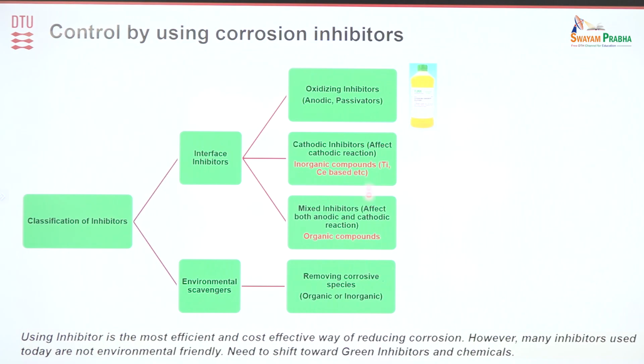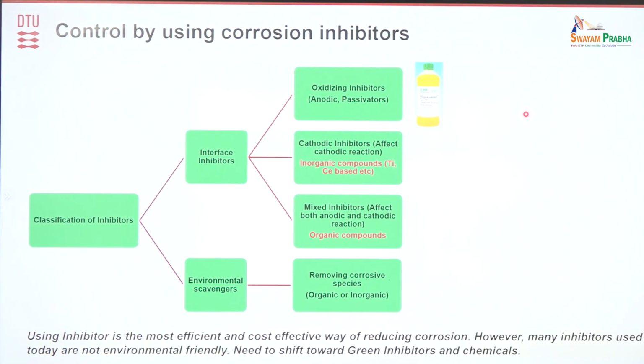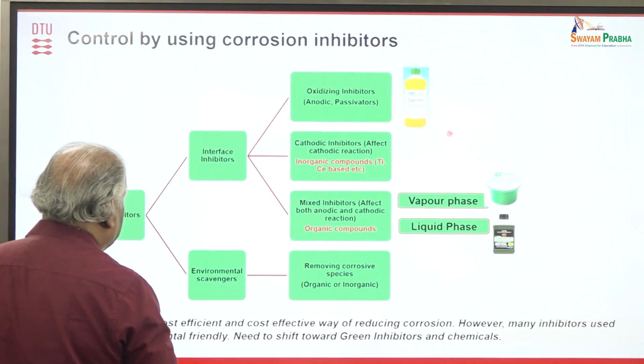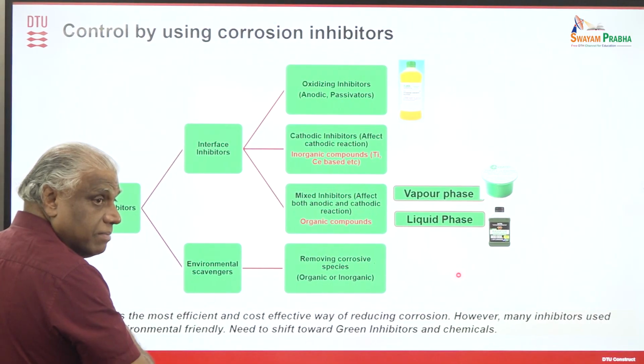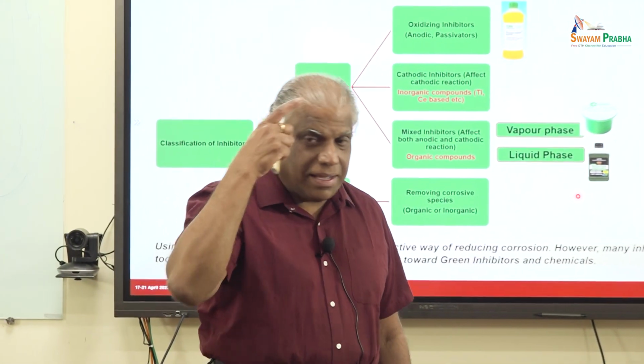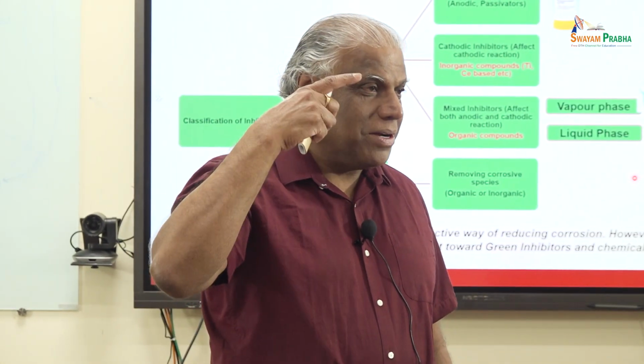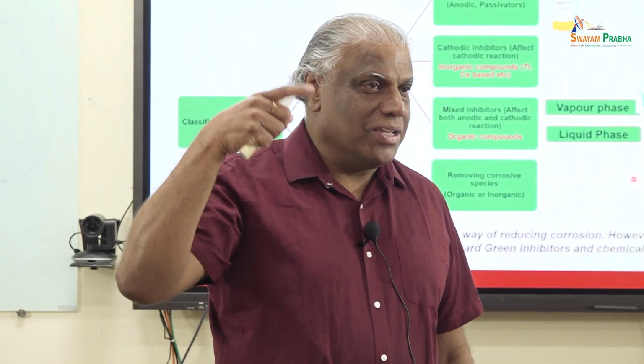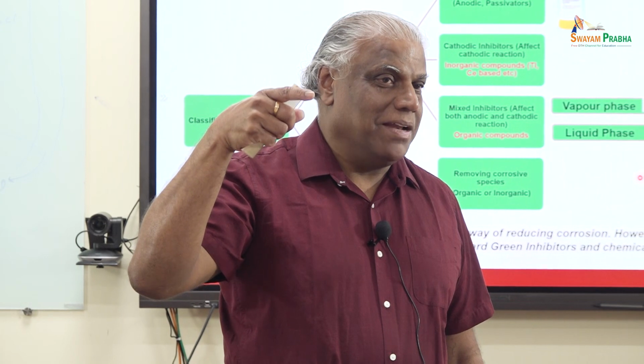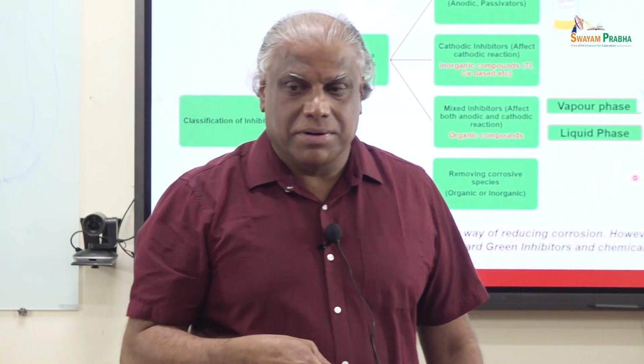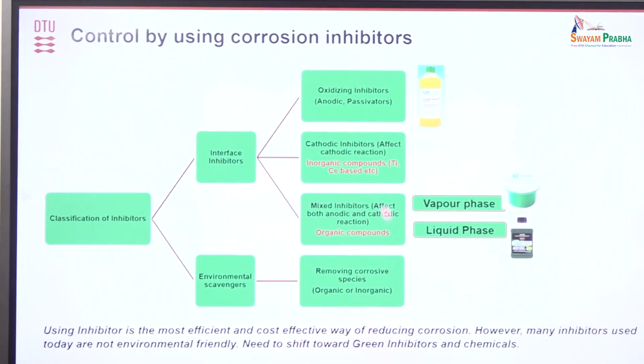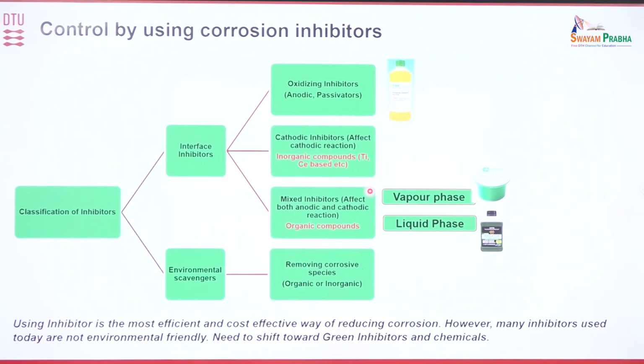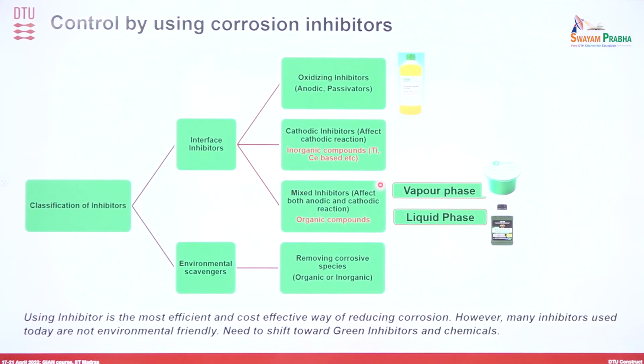But among the interface inhibitors, there are oxidizing inhibitors, which are usually for the passive metals, anodic and passive metals, where you can do the oxidation, what I mentioned earlier, using the curve I showed, increasing the oxygen concentration. Other one is the cathodic inhibitors. Basically, the cathodic inhibitors are blocking the cathodic site. That's why I mentioned that earlier. Whenever you think about the steel surface, the more important thing is the cathodic part, the manganese sulfide. Or if you are thinking about aluminum alloy, the more important part is the iron containing intermetallic particles. If you can block that, automatically you block the cathode reaction. So the cathodic inhibitors are basically something which comes and sits on the cathodic part and acts as a barrier, and that way the corrosion will not occur.